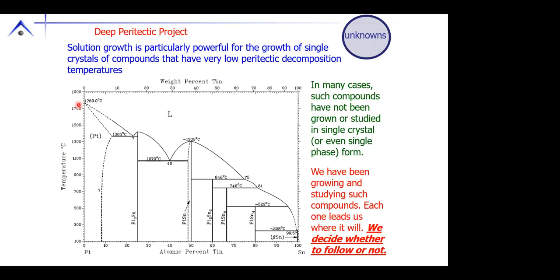Okay, so platinum melts at a high temperature, and once we're beyond 50-50, we have this cascade of compounds that decompose peritectically. PtSn4 is a compound that if you actually try to grow it by slowly cooling a stoichiometric melt, you'd first grow Pt2Sn3, then PtSn2, then PtSn4, and end up with a little tin left over. It would be an ugly mess.